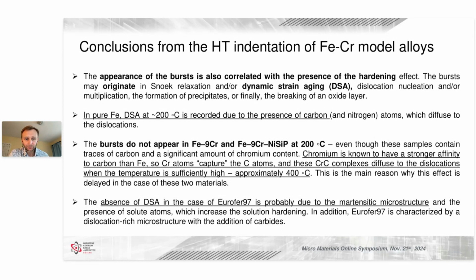These complexes cannot diffuse at 200 degrees because the temperature is too low, but the diffusion starts at 400, and this is what we see again at 400 degrees: carbon-chromium complexes are diffusing to the proximity of the dislocations. They are locking their movement, preventing them from spreading around, and the bursts we observe are due to this interaction and release of the deformation suddenly when the critical point has been reached.